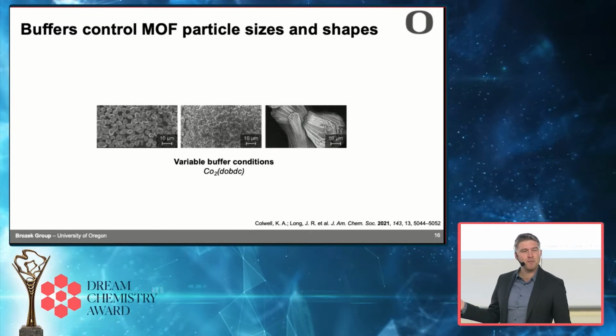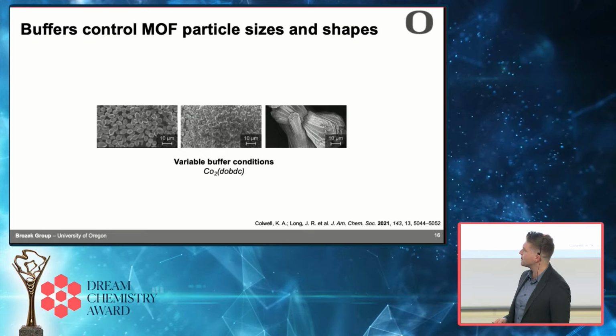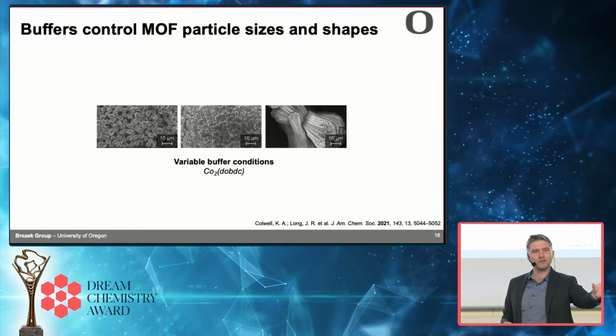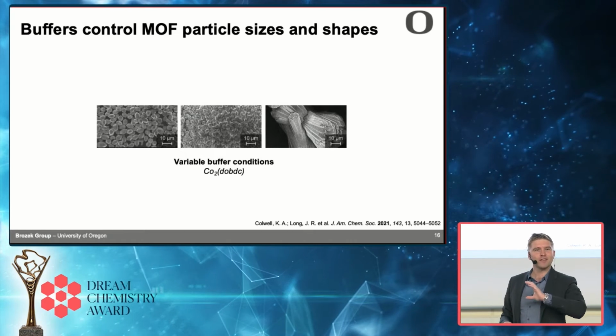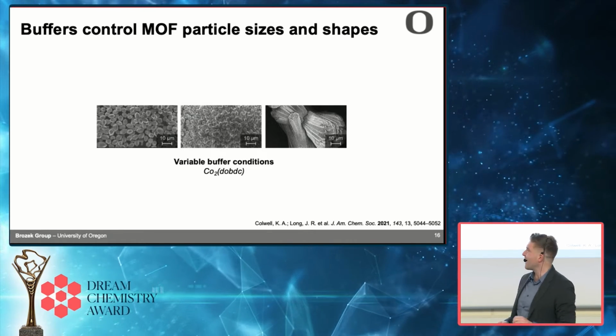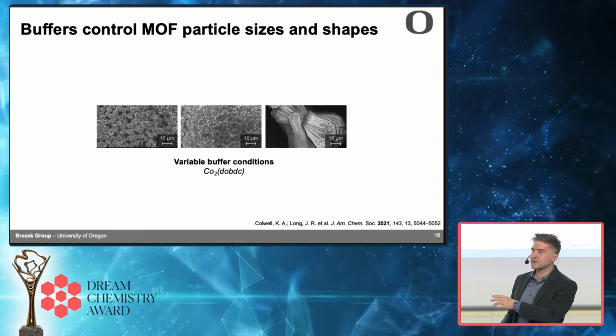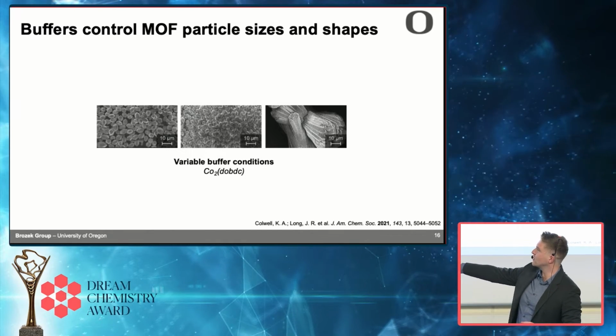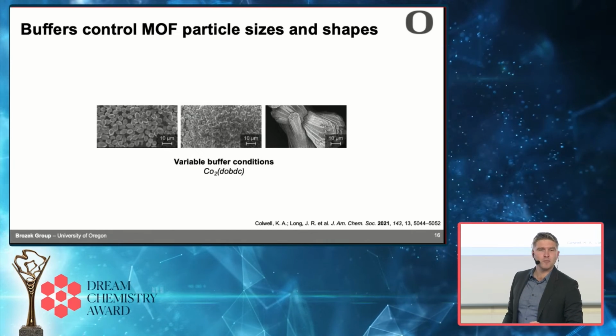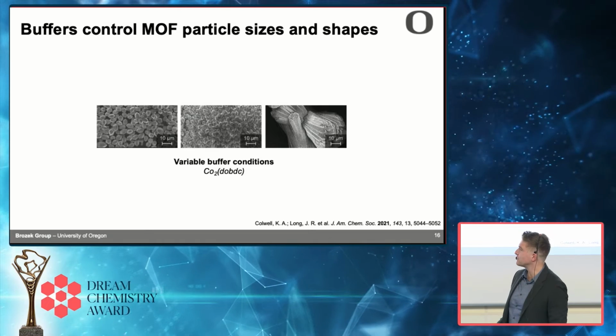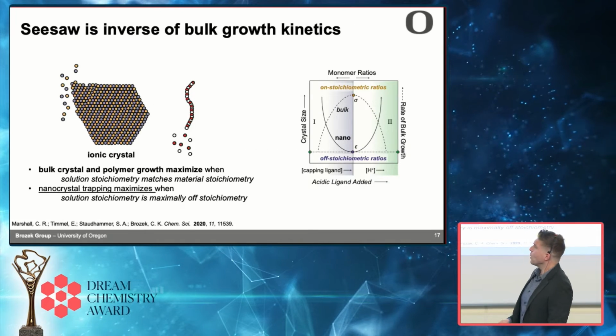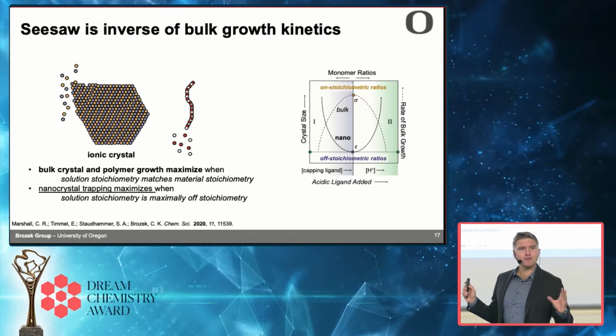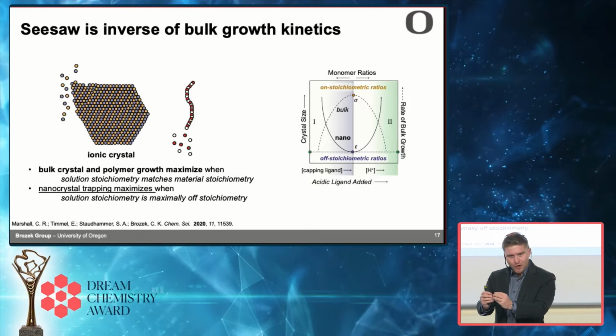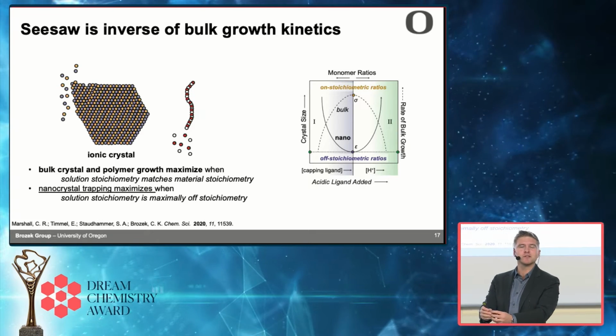Other people have started to pick up on this idea. So Jeff Long's lab had this really nice paper showing you could use an off-the-shelf typical biochemical buffer and apply it to a different set of MOFs. And you have a huge control over the particle sizes as well as their morphology. So that was nice. Well, we want to take a step back and realize we're not just studying this really small little niche field of MOF nanocrystals.